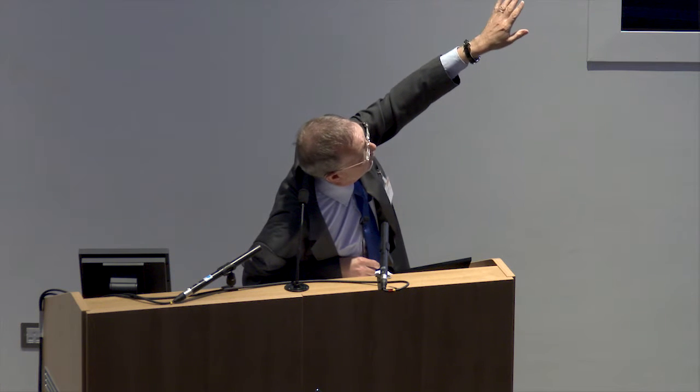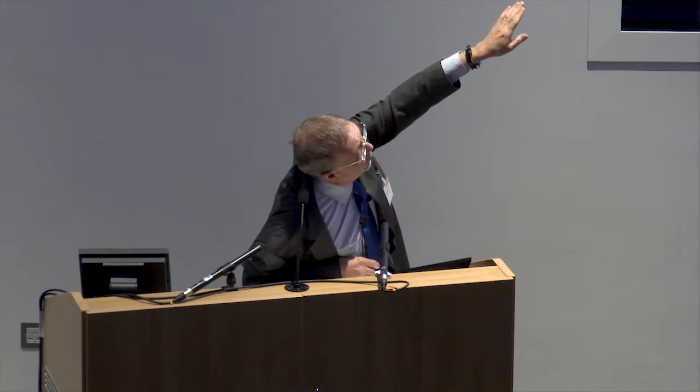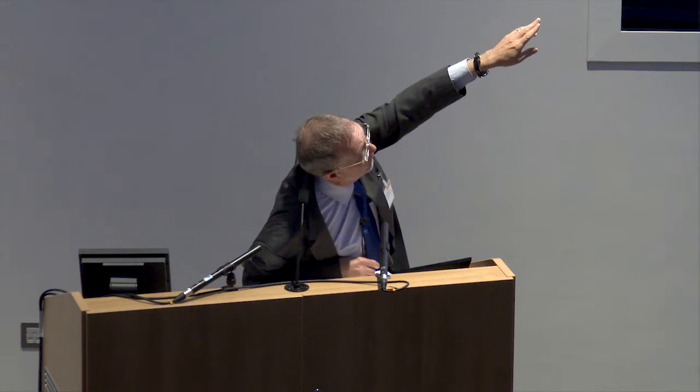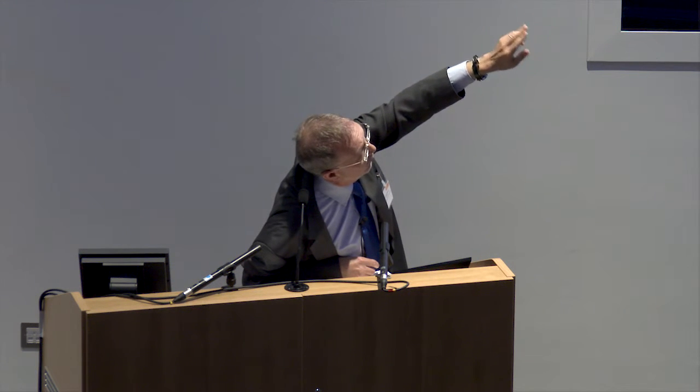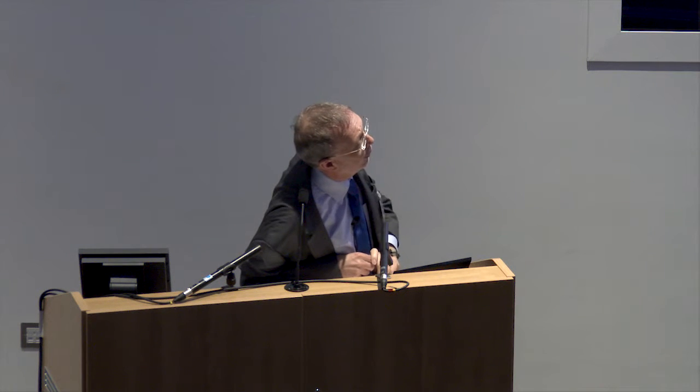And then looking at different layer thicknesses before you scan. So if you're laying down a 30 micron skin, after two layers, you'll be doing 60 microns in the core. Or after 3 layers, you'll be doing 90 microns in the core. Or after 4 layers, you'll be doing 120 microns, right up to 150 micron layers.